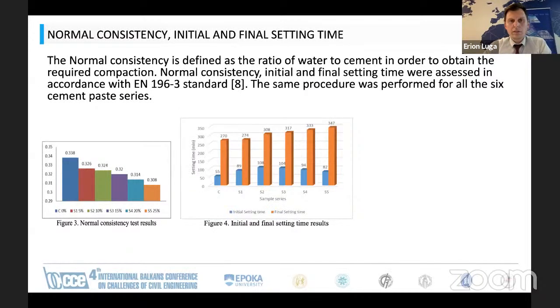Regarding the normal consistency, the test was performed in accordance with EN 196-3, and the same procedure was done for all the 6 series. As we can see in the figure on the left, the water content decreases as the slag amount increases. The water content for the normal consistency is about 0.34 in the beginning, and with the use of 25% of slag, it reaches 0.3, which means that it decreases the requirement of water by adding slag.